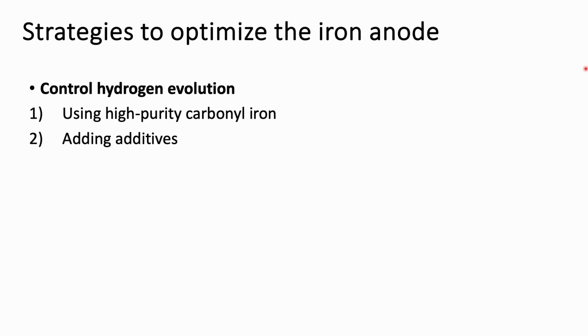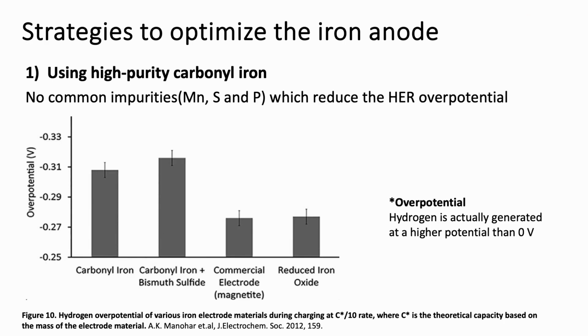There are some strategies to control the hydrogen evolution. The selection of raw materials for the fabrication of the iron electrode is important in suppressing hydrogen evolution. It's proposed that there was an increase in charging efficiency with the high purity carbonyl iron electrode, and it's attributed to the high overpotential for hydrogen evolution on carbonyl iron. High purity carbonyl iron does not have any of the common impurities such as manganese, sulfur, and phosphorus that can reduce the hydrogen evolution overpotential.